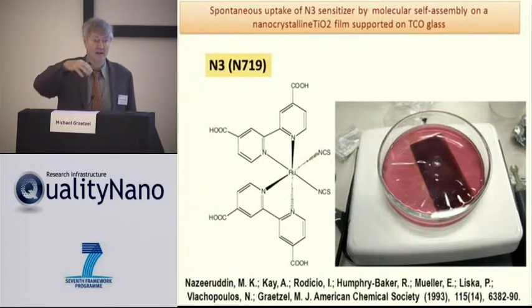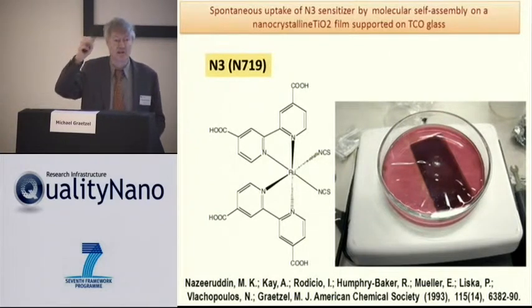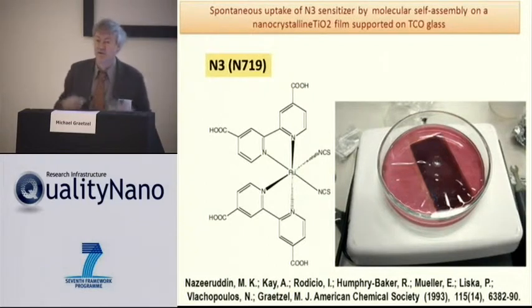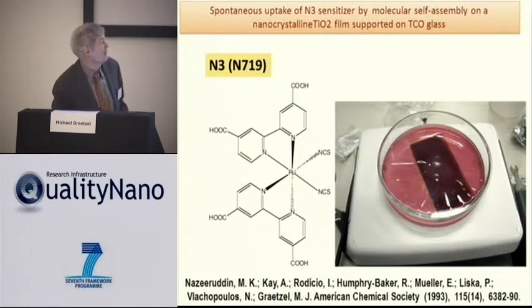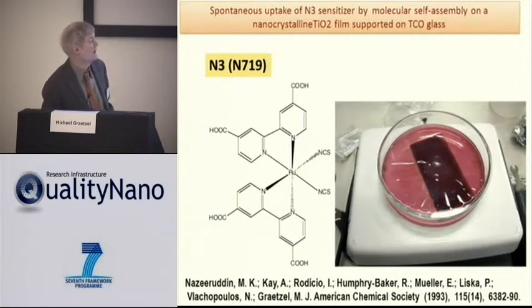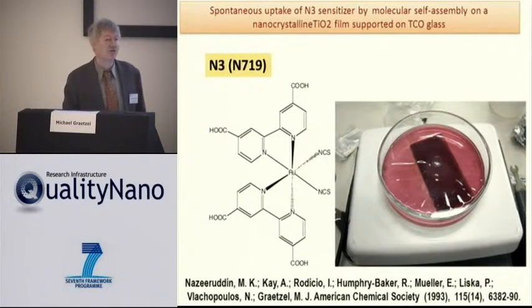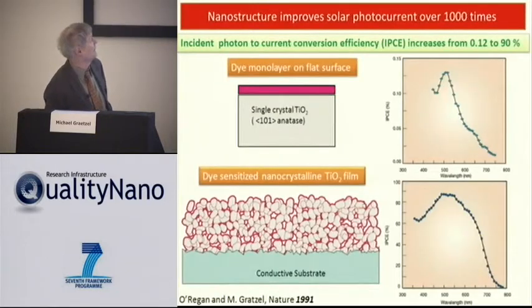Why is that? Well, the internal surface area is huge. It's almost several thousand times bigger than the projected surface area. And so that means when we put a dye on, we get very good light harvesting because we have a high concentration in those films of the light harvested. And so this effect is shown here.